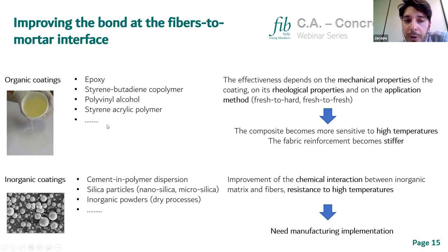By doing that, we are adding a material, which is a polymer, which suffers the high temperatures. So we are creating practically an FRP within an inorganic mortar. Of course, the effectiveness depends on the mechanical properties of the coating, on its rheological properties, and also on the application method. We can apply the mortar on the fresh coating or when it is already hardened. In this case, the composite becomes more sensitive to high temperatures, and also the fabric reinforcement becomes stiffer. So it is more difficult, for example, to apply the system on curved surfaces.